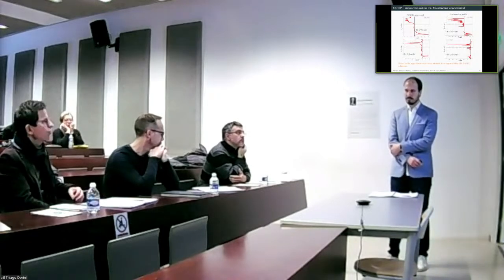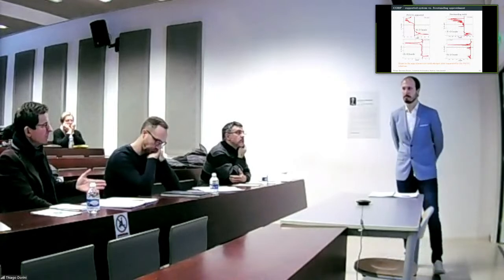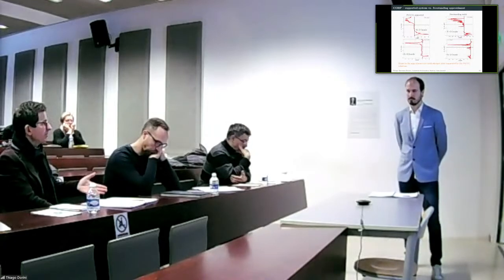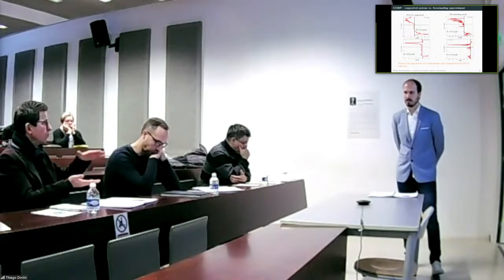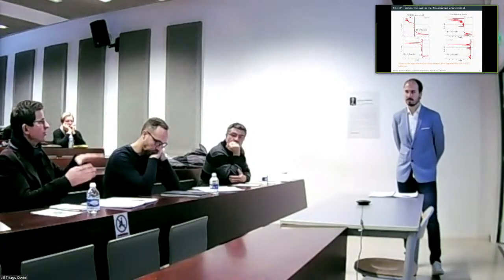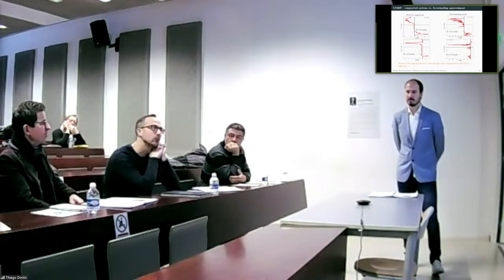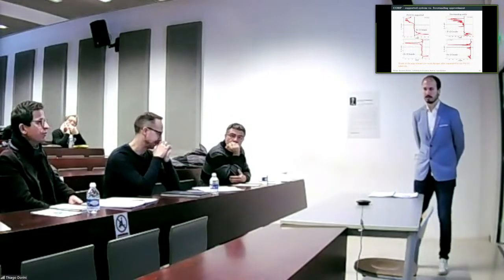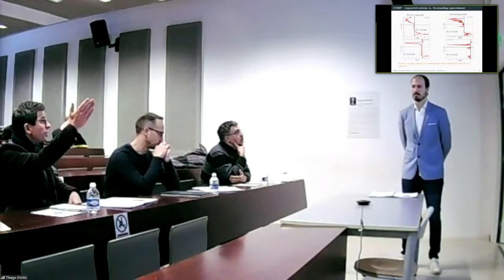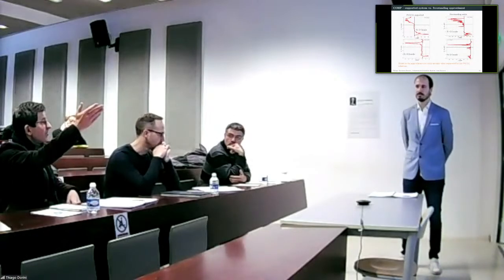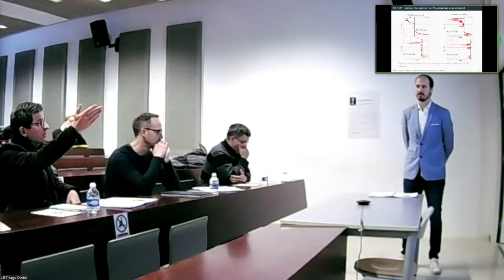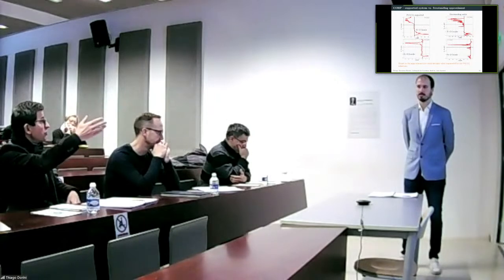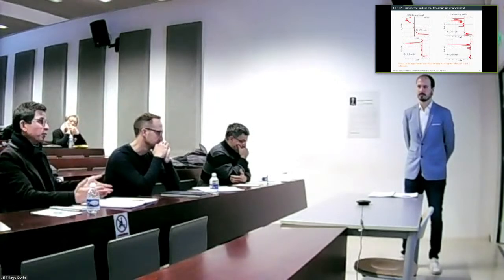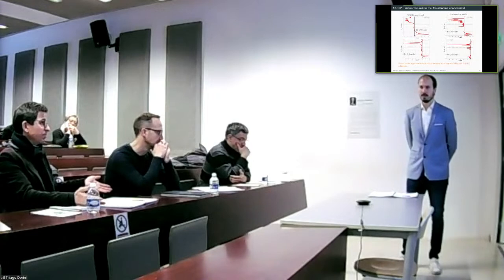For two reasons. First, I have the impression that it is oxygen rich. Yes. You have chosen two oxygen rich terminations, which makes the film overall oxygen rich. Yes, you're right. But judging by the experience we have just discussed with indium oxide and palladium, if it is oxygen rich, it does not produce the favorable structures.